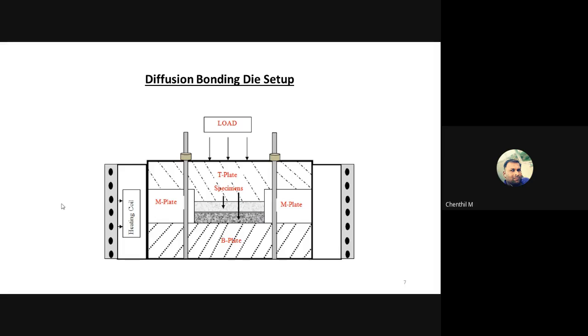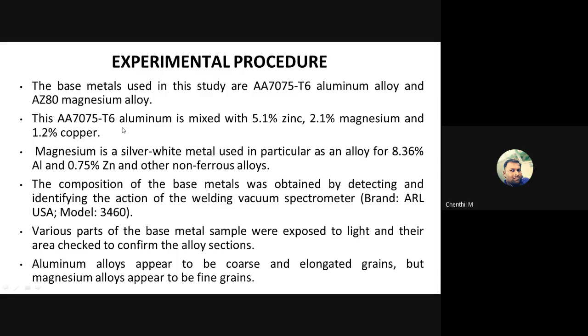I'll just show this. This is the die setup. This is the bottom plate, the top plate, and the middle plate, where the specimen is kept and load is applied. That load is considered in terms of pressure, and it is held for the time I mentioned earlier. The furnace maintains the temperature. So this is the base material we used. The aluminum contains 5.1% zinc, 2.1% magnesium and 1.2% copper. The magnesium is a silver-colored alloy with 8.36% aluminum and 0.75% zinc, which is a non-ferrous alloy.